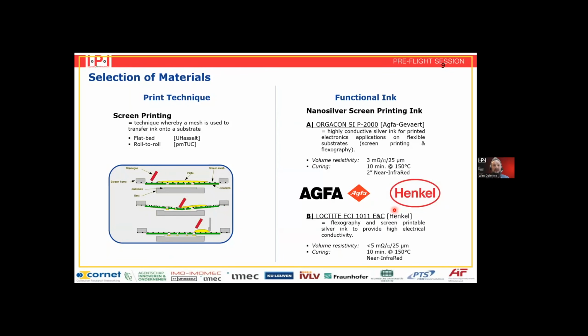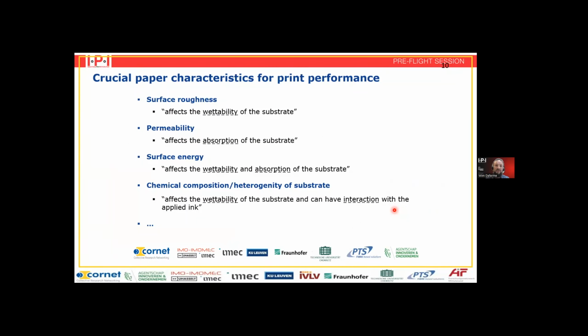In the end, we use different printing techniques as well, also a few from the companies, to test if that works on the fiber-based substrates. Here we only use screen printing, and for the inks we used an ink from Agfa, the Orgacon ink, and an ink from Henkel, a Loctite ink, and then we looked at the interaction on the substrate.